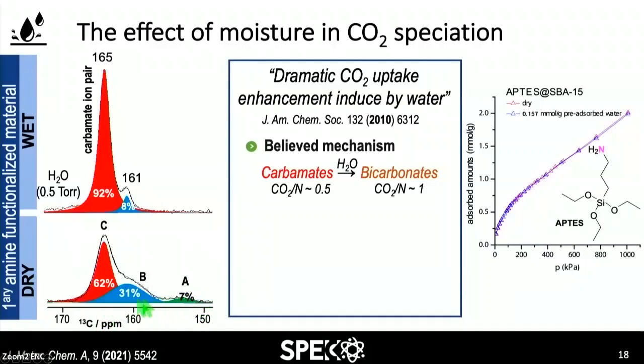And if you look at this spectra compared to the one under wet conditions, and in this case we used 0.5 torrs of water, you can see that species A converts into species B, and species B converts into species C, which is represented here in red. I will, in the next slide, show you this in more detail. So the question remains, is either of these species bicarbonate? How can we be sure?